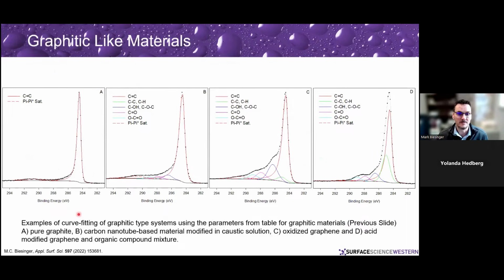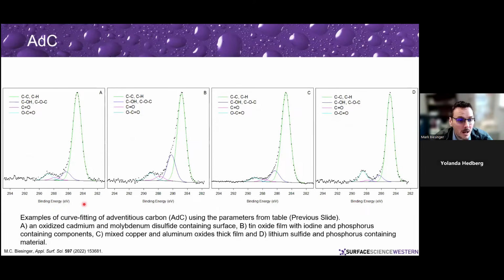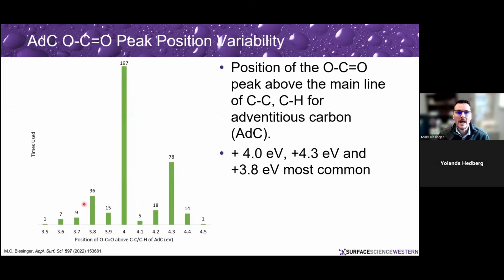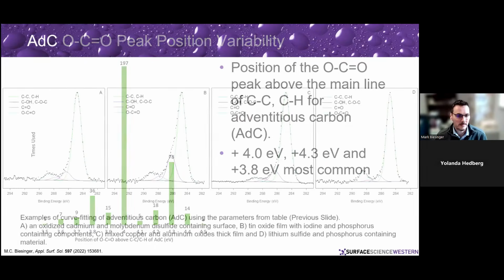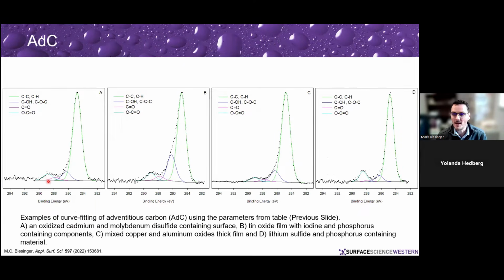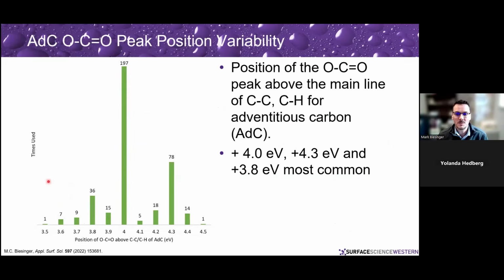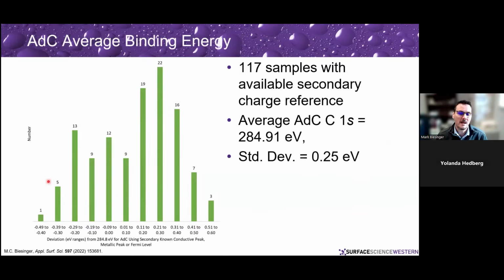And these are just some examples of graphite-like materials and how that same curve fitting, with the same parameters for all of them, gives you different values of the amounts of different oxygen type species that are present on those samples. Again, for adventitious carbon, these are the same fitting parameters, and you can see how the carbon does change. It kind of moves around a little bit. You get more or less oxygen sticking on different surfaces, more or less oxygen components on there. We looked at the positioning of this high-end peak and how that changes. We looked at those sorts of things, trying to understand what the adventitious carbon looks like.